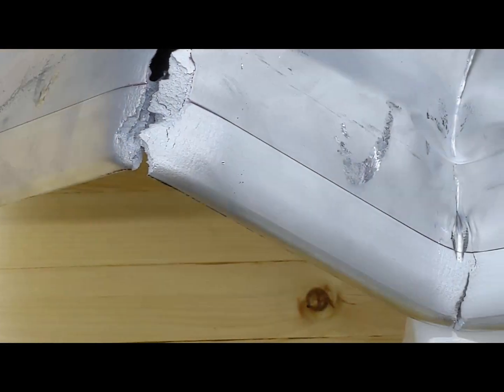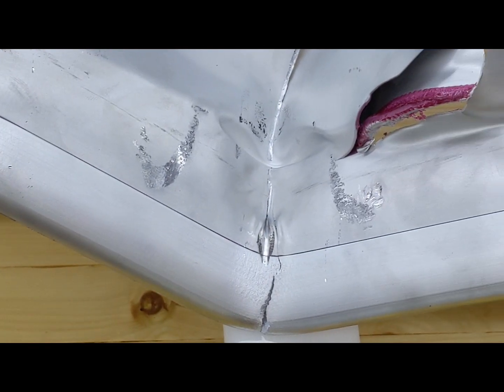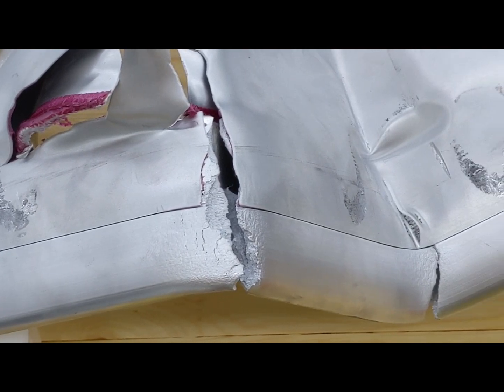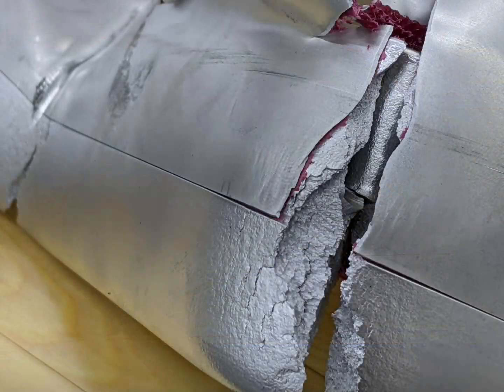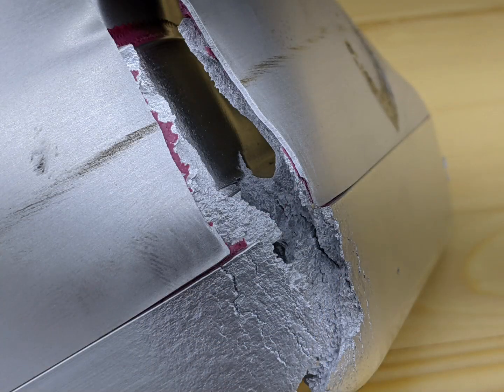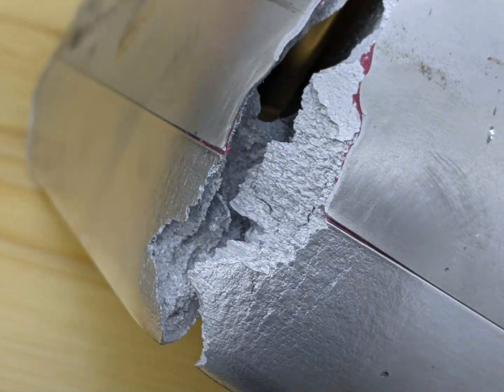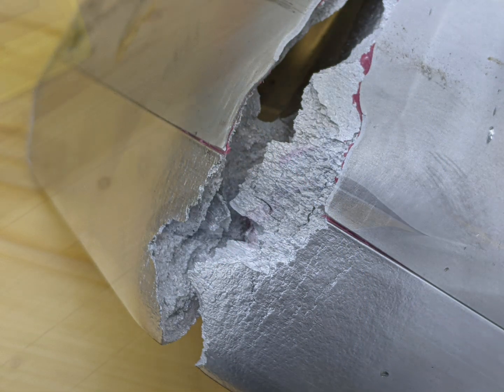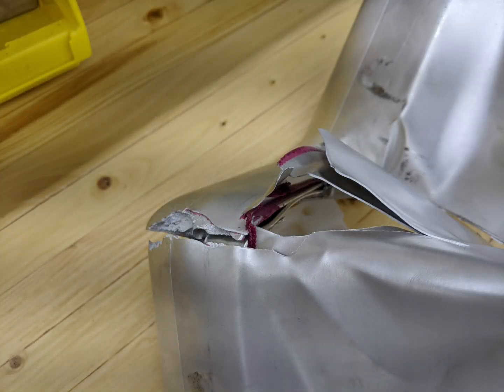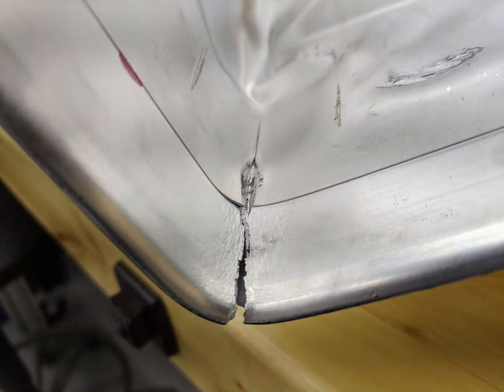There are some types of forces that the blades will never see during a typical flight, but some destructive testing is a good idea to prove the bond strength of the adhesive. Here you see a sample that we subjected to the hydraulic press, bending it in every way possible, resulting in catastrophic failures of the leading edge, extrusion, and the skins. But you'll see between these fractures there's no separation of adhesive or delamination of skins in any location.